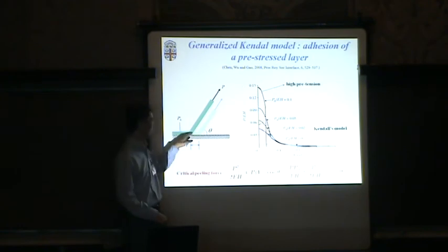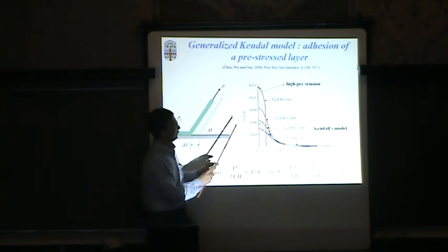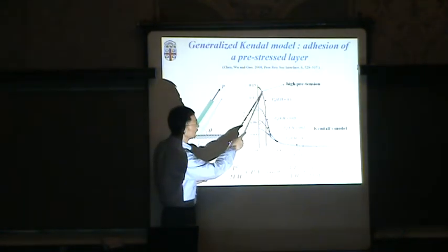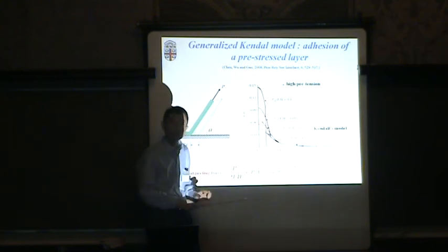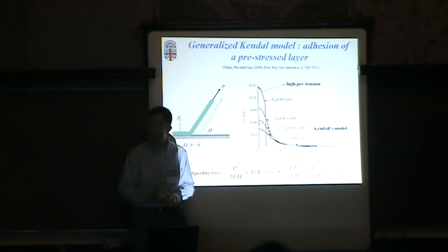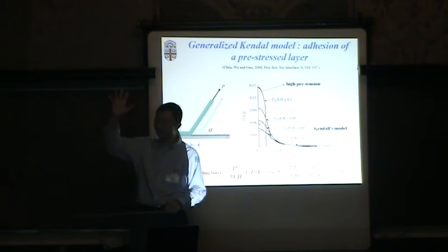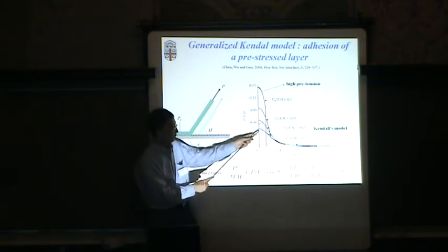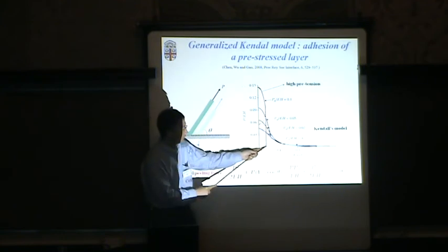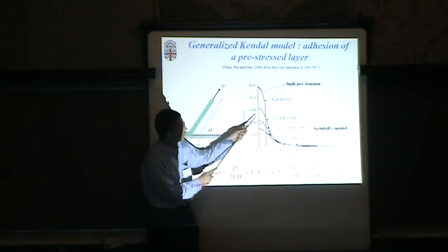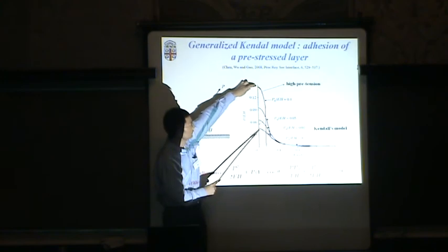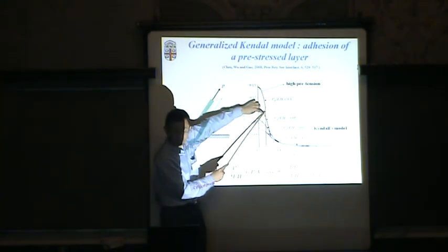But what does that mean? That means if the pre-stress is large enough, you only have very strong adhesion up to a certain angle. Once you reach that angle, adhesion is spontaneously released. It reminds us of the experiments of the gecko hand, where at 30 degrees the thing just dropped. This has an advantage compared with Kendall's original model: below the critical angle, very strong adhesion, and yet at the critical angle, it's spontaneously released.